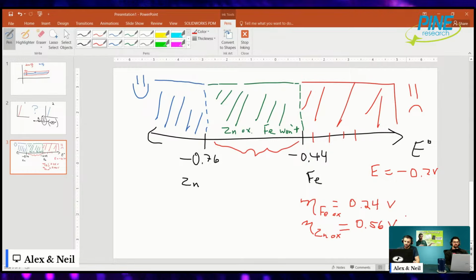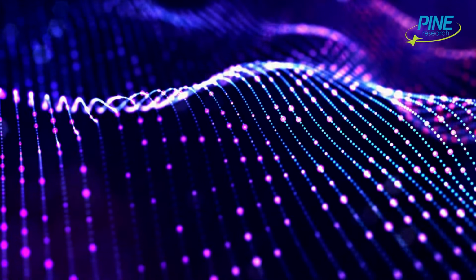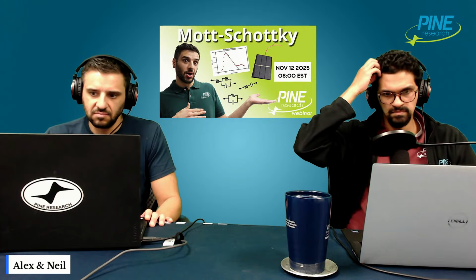So the overpotential for zinc is higher than the overpotential for iron. So there's a bigger driving force for zinc to occur, which means zinc is going to happen exclusively, or at least faster. And then once it's all gone, the iron will start to oxidize. You're taking advantage of this thermodynamics. I guess it's called galvanization, or you'd call it sacrificial anode or sacrificial metal. I'm not sure precisely what you would call it, but that's a cool way to take advantage of electrochemistry, basically. Standard potentials, exactly. So nice.